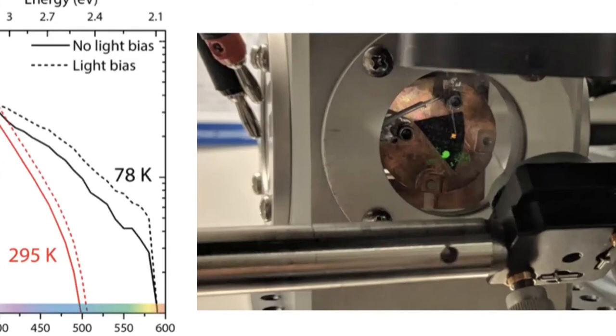And here is the quantum efficiency as a function of tunable beam wavelength, both with and without the light bias added at two different temperatures. So in both cases, you can see that above gap is right over here, just this leftmost portion of this setup, which is a few percent here. But what I want to draw your attention to is the extra quantum efficiency that we get for adding the light bias is measurable on here without going down by orders of magnitude. It is a 15 or 20% increase in the quantum efficiency that comes from this two photon